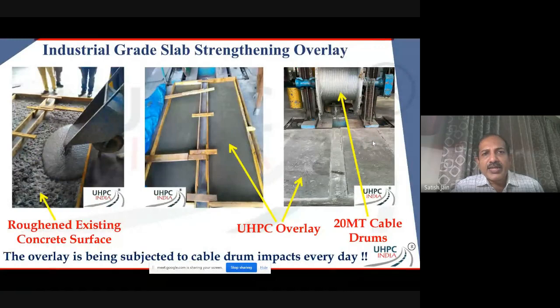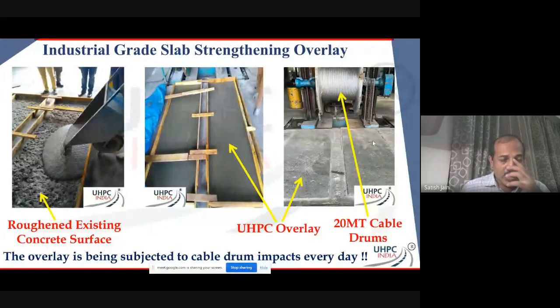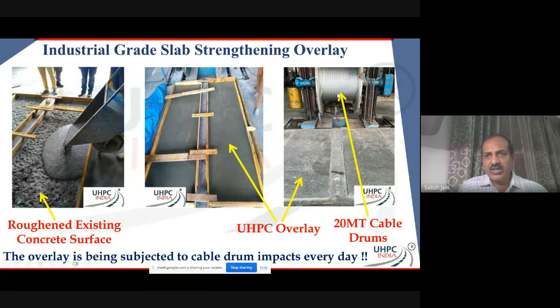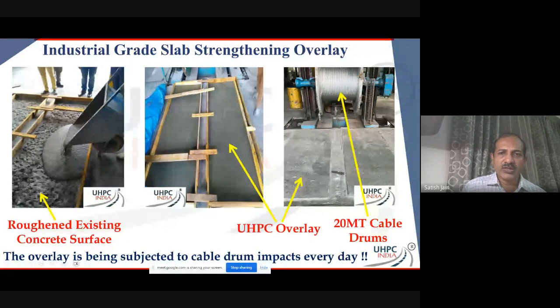A little bit of an industrial grade slab strengthening. It's not more of strengthening, it's again abrasion resistance. So here was a project where we supplied some material to it. Was a little bitty of a material, but they had huge cable drums over here, and after the entire winding was complete, about 20 metric ton bobbin would just fall down on the floor, and they had some steel plate over here, but then it would move ahead on the concrete floor, and every 6 months they had to keep redoing. So here was a solution that we were able to offer, where a little portion was still roughened up and UHPC was poured over it and cured.